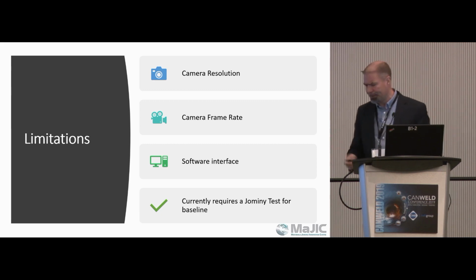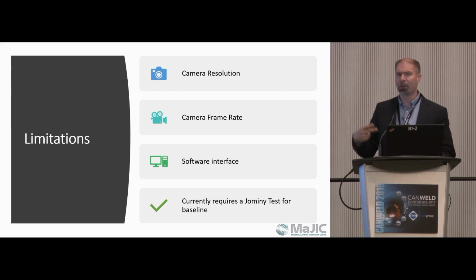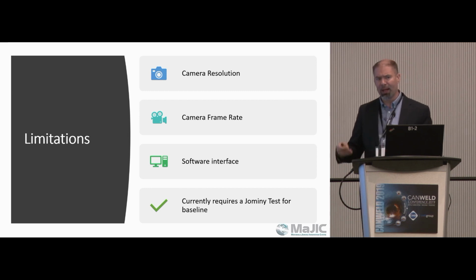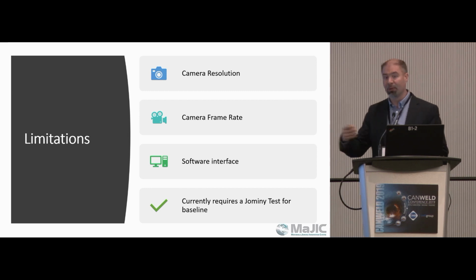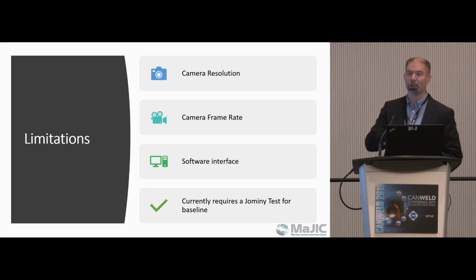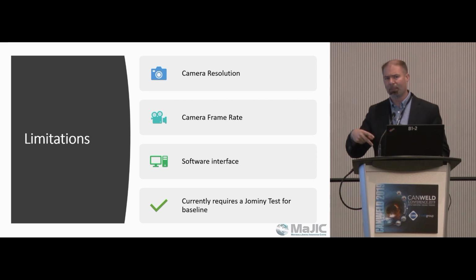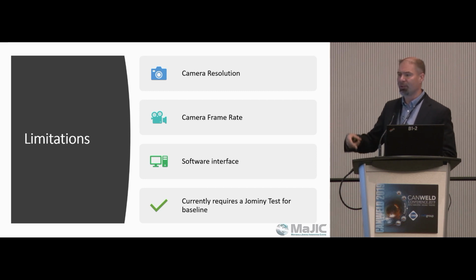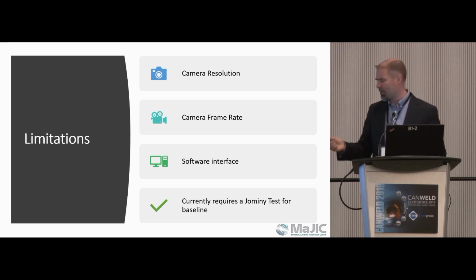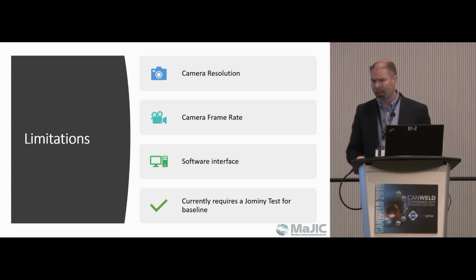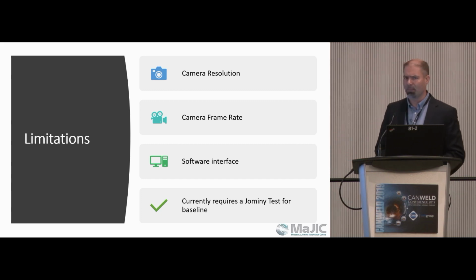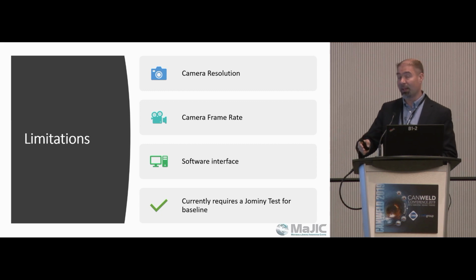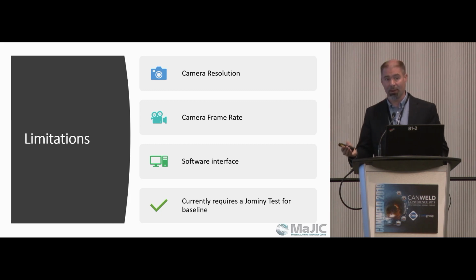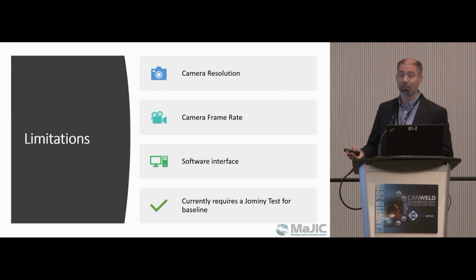Currently, all of the predictions that we're making are based on actual Jominy data that we've done. So in order to look at a particular alloy and predict the hardness on a weld on that alloy, we would need to first have a Jominy end quench. There is some opportunity to expand it out from there using the calculation method in the ASTM A255. We have yet to correlate that with the data.